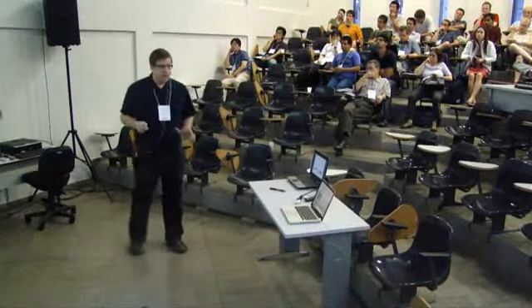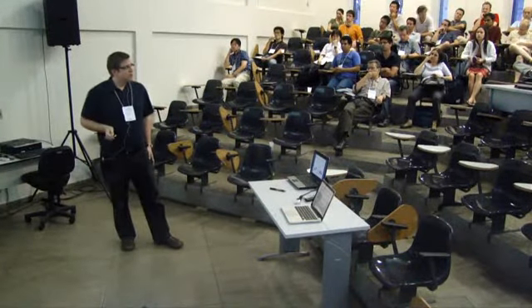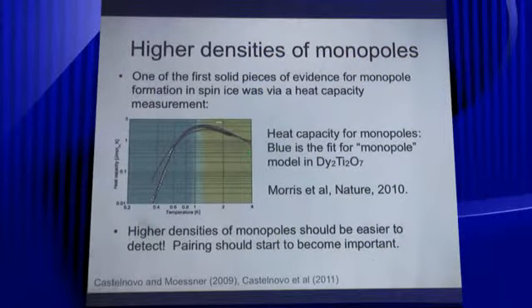So actually, muons aside, one of the first bits of evidence for monopole physics was looking at the heat capacities. This is a fit done for dysprosium titanate, so the blue is this monopole fit that they did. What we did is we took basically the Debye-Hückel theory and used it with dysprosium titanate to see how good of a fit it would be, right? And what we found was that, I know Claudia gave us a nice talk showing that pairing is not very important for these pairs of monopoles at low temperatures, but it actually is extremely important for dysprosium germanate, as I'll show in the next few slides.